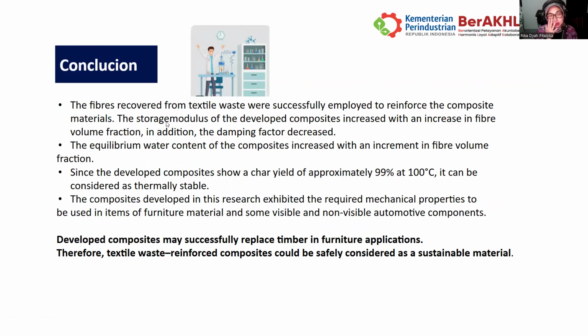Okay, so now we are coming to the conclusion. As the conclusion of the journal, it mentions that the fibres recovered from textile waste was successfully employed to reinforce the composite materials. The storage modulus of the developed composite increases with the increase of the fiber volume fraction, and in addition, the damping factor decreases. Conclusion number 2 is that the equilibrium water content of the composites increases with the increment in fiber fraction.